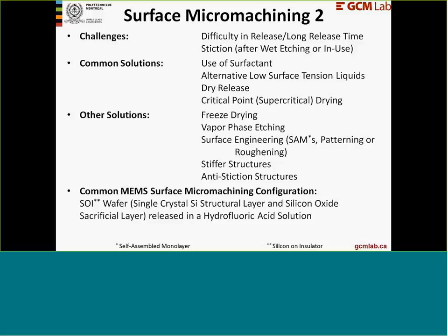You might encounter some challenges in surface micromachining release steps. Very large structures or structures with very small release holes are difficult to release, and it will take a long time to release them. Another problem is stiction that happens due to the surface tension of liquids, normally water, used to rinse the device after being released, resulting in collapse of the structure that was supposed to be freestanding.